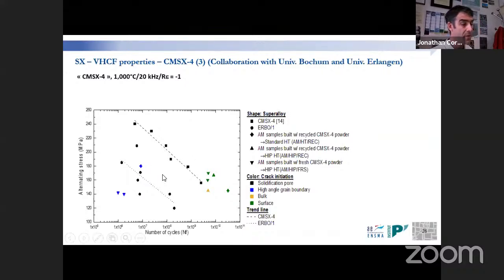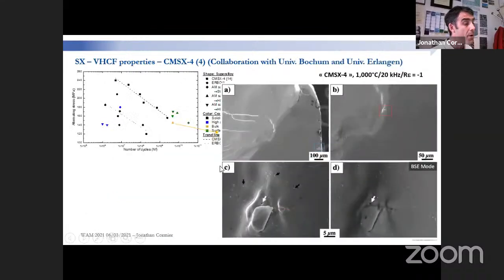So that's something we also have to work on, probably using another mode of VHCF testing using a pulse mode. But from the successful tests, you can see that the AM material performs very well, well in excess of, let's say, our reference materials with small pores. And we have been able to observe crack initiation from an internal site, which should be, and we are not 100% sure about that, a low-angle grain boundary because it was a HIPed specimen.